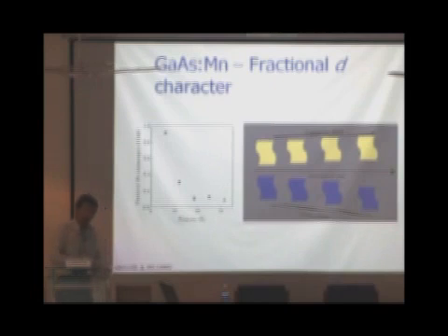Do we retain the half metallic character or not? The answer is that we do, coming from the bulk, up to about 20 angstroms, or 2 nanometers, we do retain these properties, but then it seems to drift. I'll just schematically explain that.